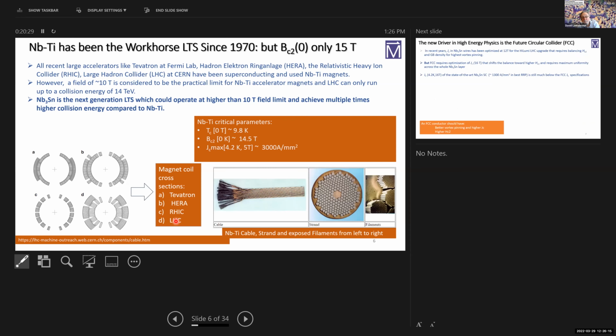All of these used niobium titanium. And actually, the key preferred form here is to have a round wire, and you cable this in a hollow flat cable, and you flatten the cable. This is a so-called Rutherford cable. Here, the copper, which is around each of these filaments, has been etched away, and so the black here are the niobium titanium filaments.